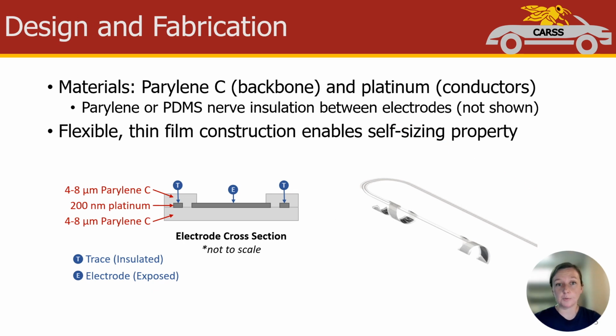The cuff electrode will be made of Parylene C as the backbone and insulation material, and platinum as the conductive electrode material, with either Parylene or PDMS insulation between electrodes to contain the electric field during stimulation. All of these materials are compatible with standard microfabrication techniques and are commonly used in medical implants. The image on the left shows a cross-section of the thin film layers in the device, illustrating the approximate geometry.